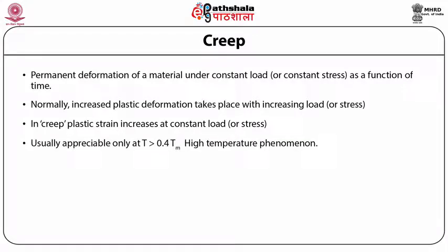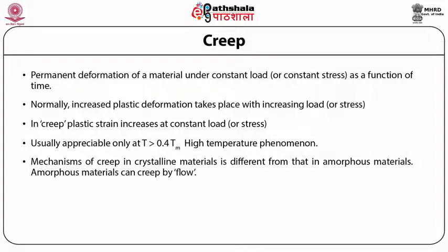Creep is usually appreciable only at temperatures greater than 0.4 Tm, that is, it is a high temperature phenomenon. The mechanism of creep in crystalline materials is different from that in amorphous materials. Amorphous materials can creep by flow.